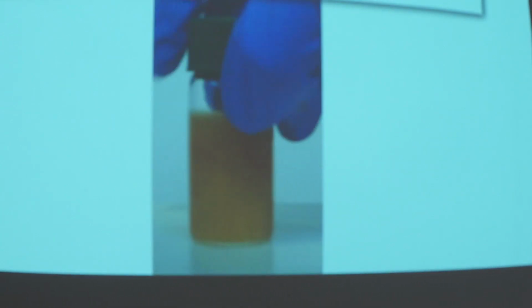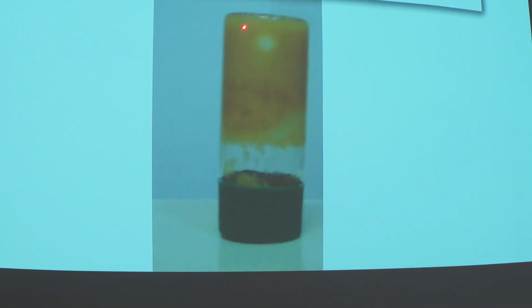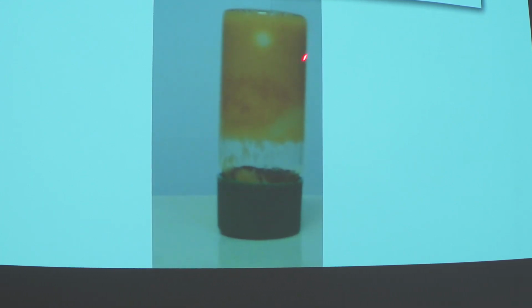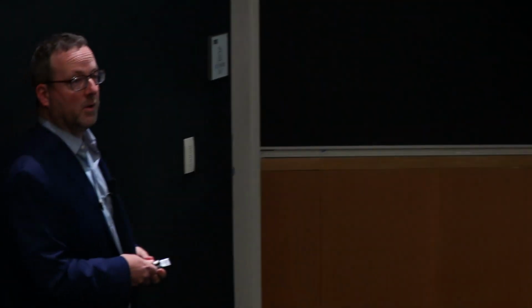And in case you can't quite see what's going on, we'll flip it over here. The little stir bar is trying to stir, but so that's polymer. We make this highly crystalline S enantiomer of the polymer. And then left behind in virtually 50% yield is the R enantiomer. So we're super excited about this catalyst for the reason that we started it, which is that we now have a great way to make optically active epoxides without throwing away the other half of our material.